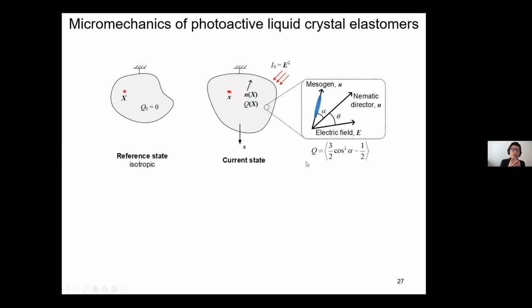Now, we can understand this. As a matter of fact, there's actually a very limited micromechanical model of these materials, especially when the material is undergoing both light and mechanical stress, okay? So we just derive a classical finite deformation framework. You have a reference state, which is in a high temperature isotropic state. And then we have a current state, which is in a room temperature or any temperature nematic state.